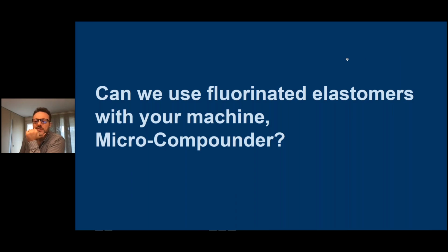Okay, can we use fluorinated elastomers with your machine, the Micro-Compounder? Yeah. I think the real question is if our machine is resistant to chemicals, because as you know, fluoroelastomers can sometimes generate corrosive components which could interact with the metal of your machine. First of all, the barrel of our machine is made out of a special type of steel. It's very strong. The hardness is more than 60 Rockwell-C, I think 63, 64, it's like diamond. Therefore, mechanically, it's nearly impossible to damage the barrel.